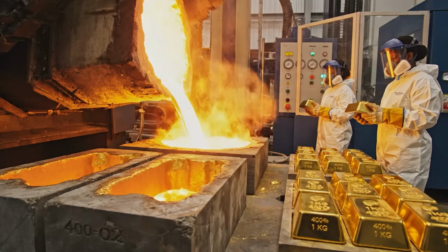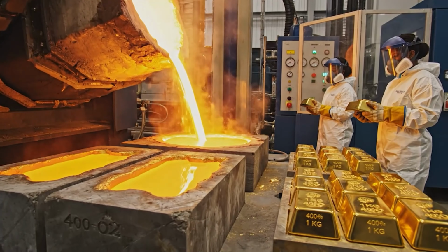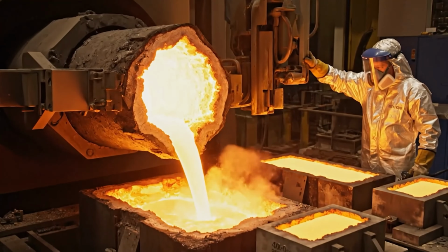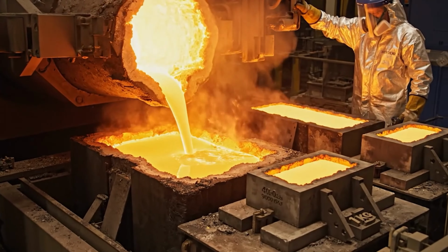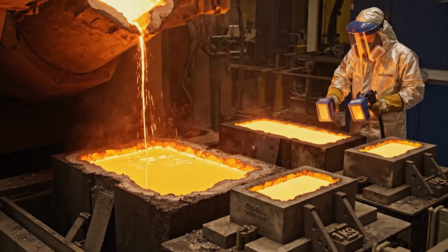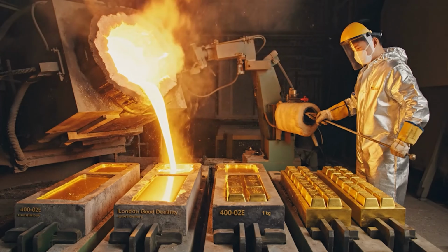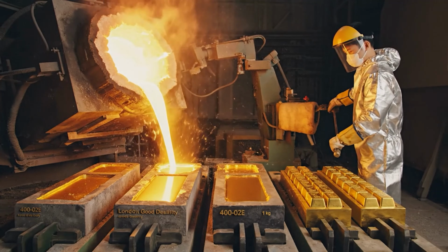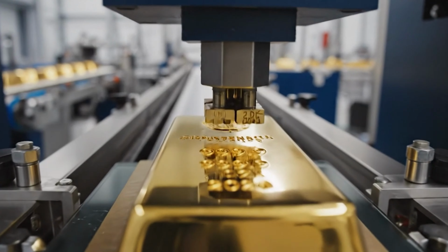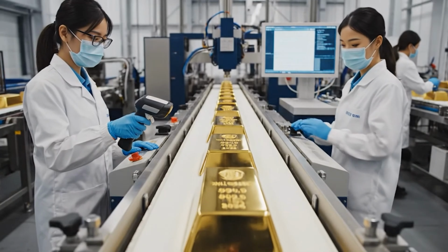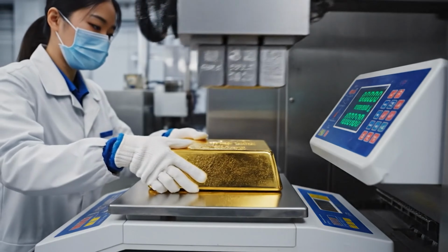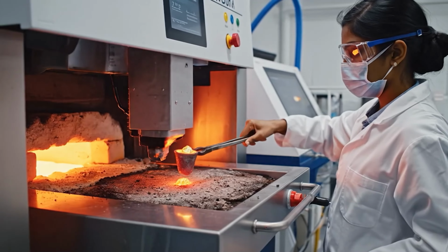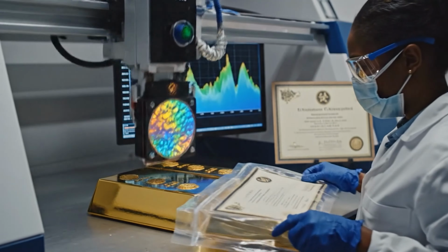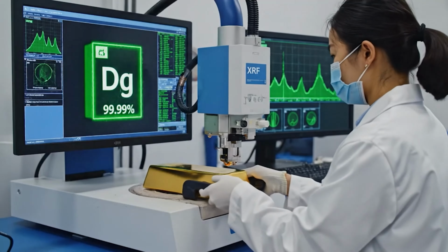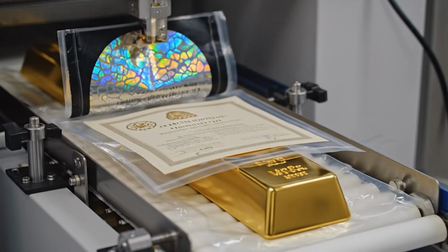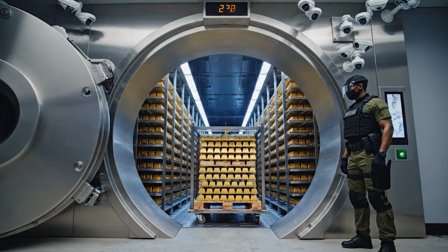Pure gold is remelted in induction furnaces under vacuum or inert gas to prevent oxidation. It's cast into bars, large 400-ounce, 12.4 kilogram London Good Delivery bars or smaller 1-kilogram bars. Each bar is weighed to the milligram, stamped with serial number, refiner hallmark, purity, 999.9, and year. Multiple assays, fire assay, X-ray fluorescence, confirm purity. Bars are sealed in tamper-evident packaging and stored in high-security vaults.